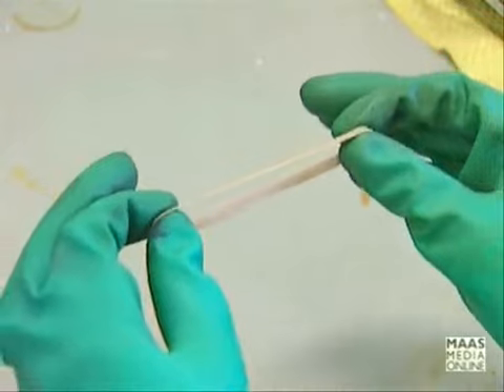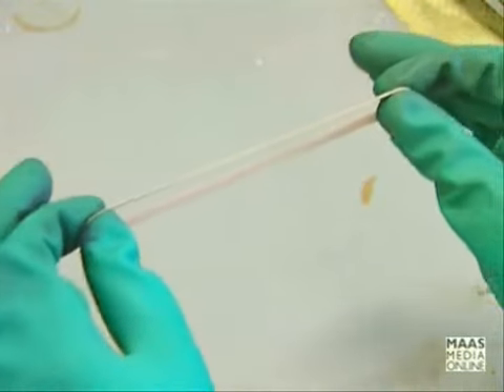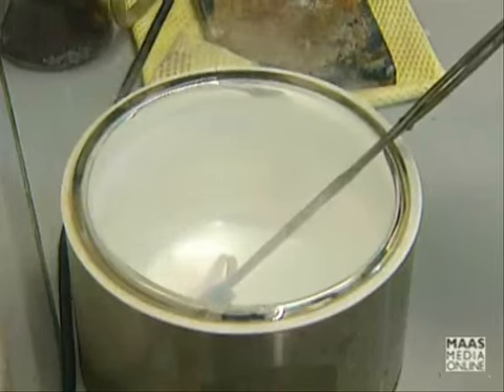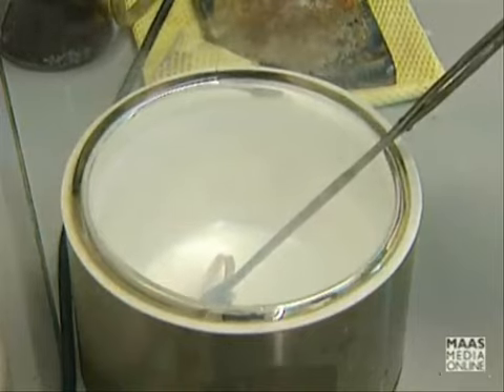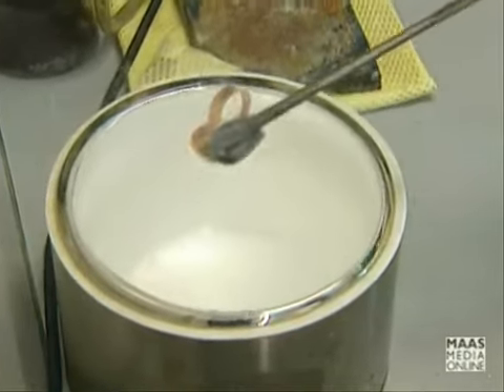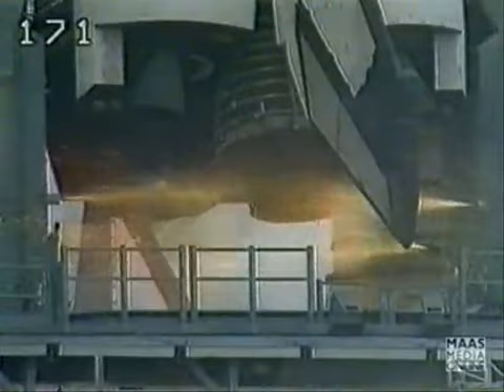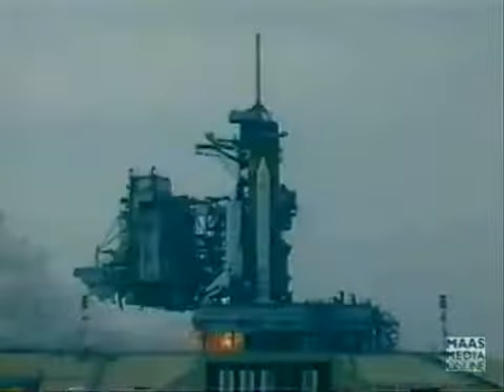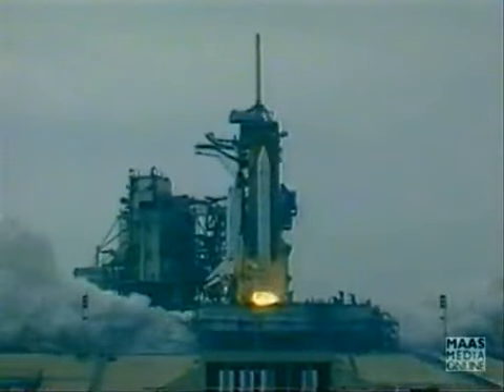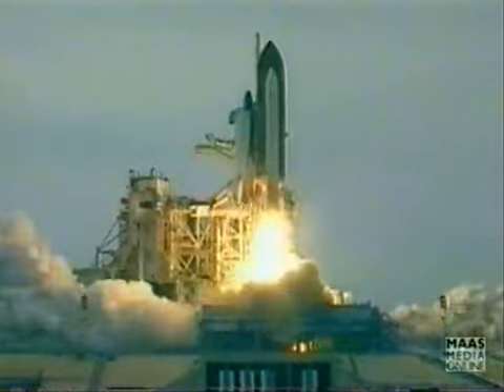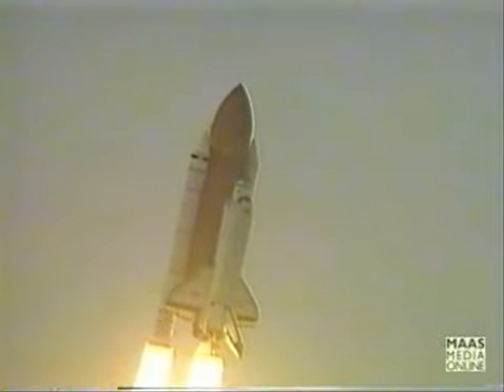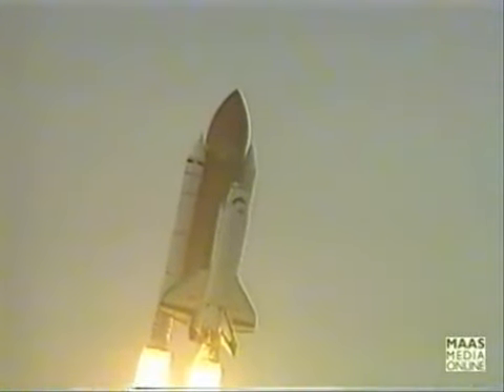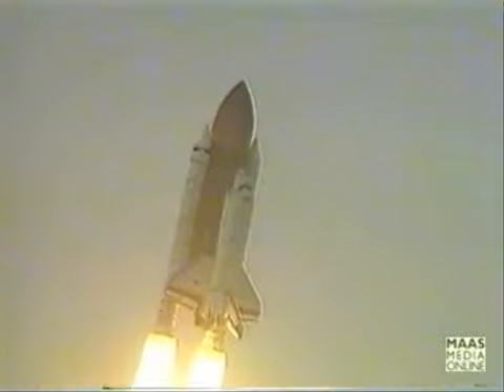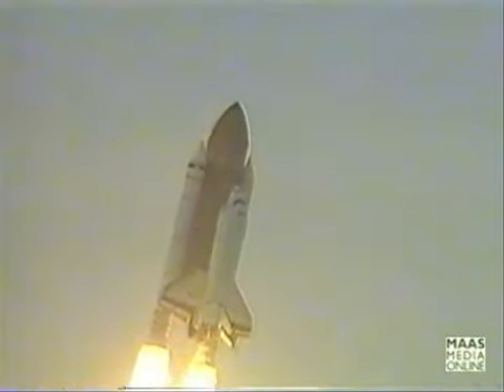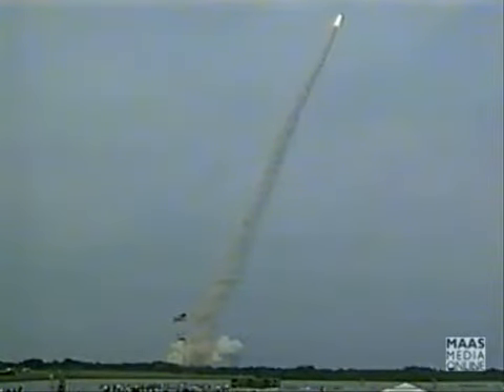At room temperature, our rubber band behaves normally because it's above its TG. But if we cool it in liquid nitrogen to below -70 degrees Celsius, the TG for rubber, it undergoes the glass transition and becomes brittle. The Challenger space shuttle disaster in January 1986 was caused by a polymeric sealing ring undergoing a glass transition due to an unexpected frost the night before. The seal became brittle during the flight, cracked, and leaked fuel with disastrous results.